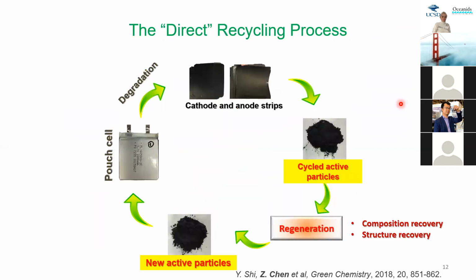Okay, so from an experimental perspective, this is exactly what we are doing. Okay, so our starting point is, if you take an example of a lithium battery, most of them will look like this fashion. You have a bag or you have a case. Okay, you have these two strips. One is cathode, one is anode. You connect it in the electrical circuit. Okay, you do charging and discharging, using simple chargers, and then you can do this process like what you are using your cell phone, charging, discharging them for like 300 cycles, 500 cycles. And then this reaction, so-called degradation, will happen, okay?